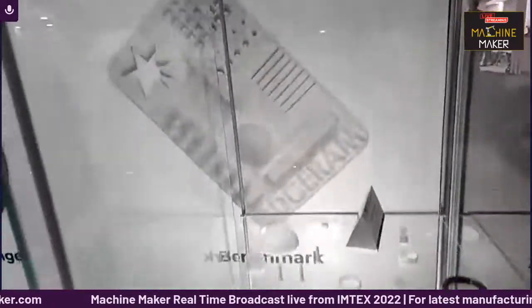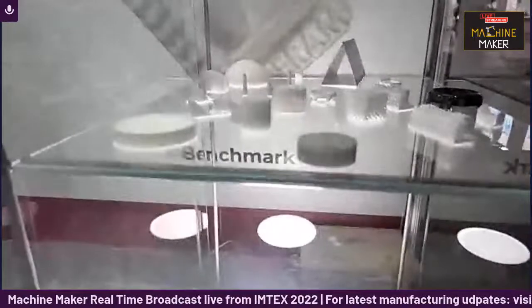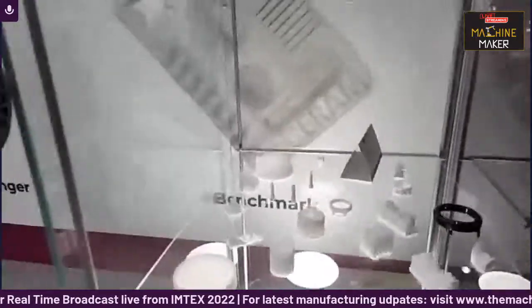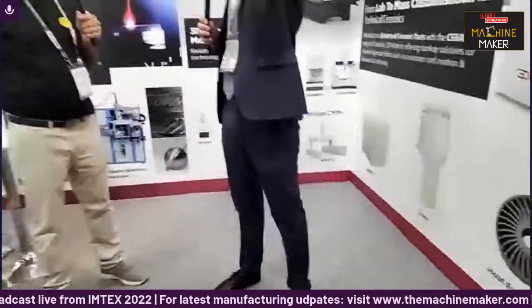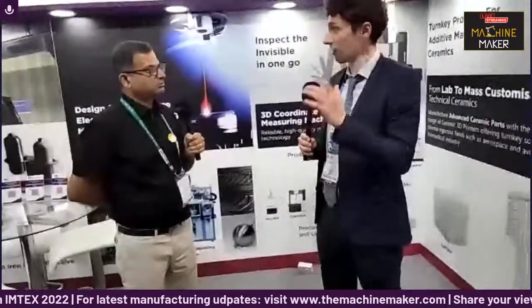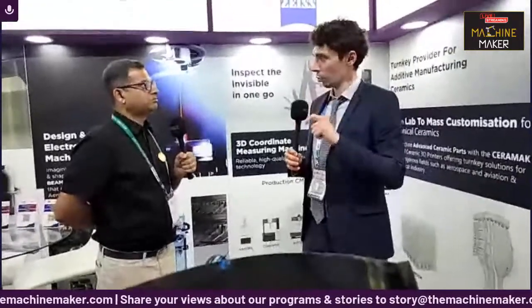Stereolithography means that we use a slurry. Slurry is a mix of ceramic powder and photosensitive resins. And then the part will be printed layer by layer from the bottom to the top, thanks to a UV laser based on the top of the printer. So our technology that we developed specifically for technical ceramic parts is a UV curing process. You have to keep in mind that after the printing, as it is a curing process, we need to do 2 thermal treatments. First one, the debinding step to burn, to remove the resins, and then the sintering step to close the porosity and to densify the part.